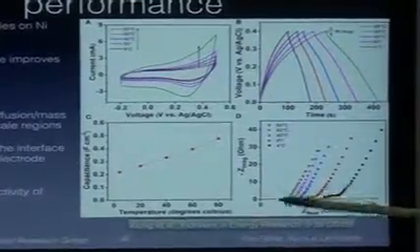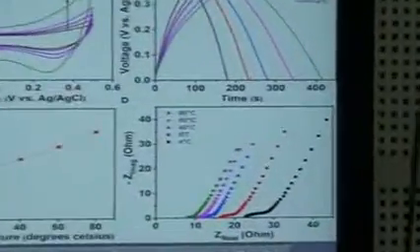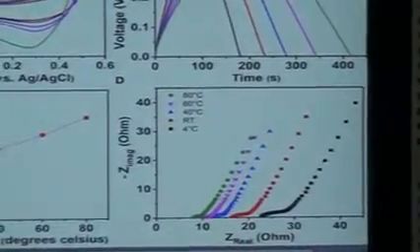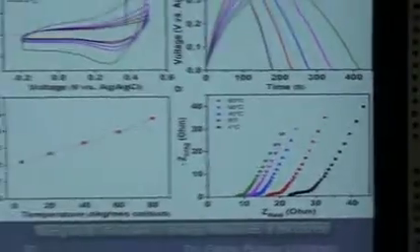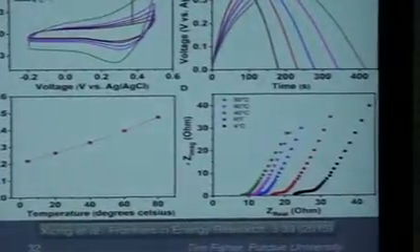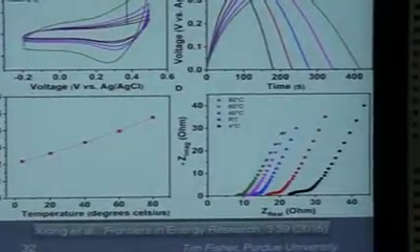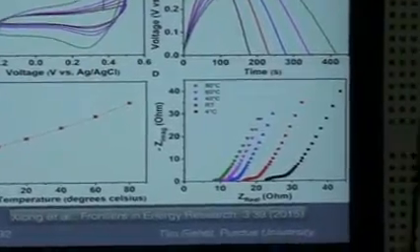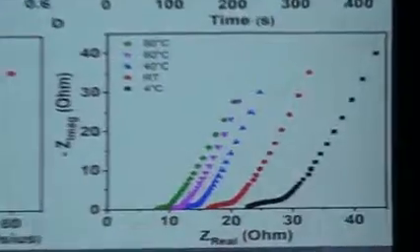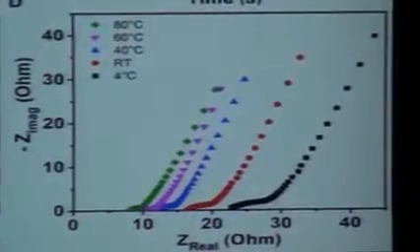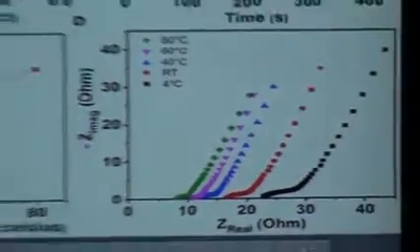And then we do also some EIS on this device, and as it gets cold, you start to see that we're having more resistivity in our material, and we start to see a clearer feature of that semicircle start to show up, right, in this kinetics controlled regime on the left side of the curve, the high frequency part of the curve.